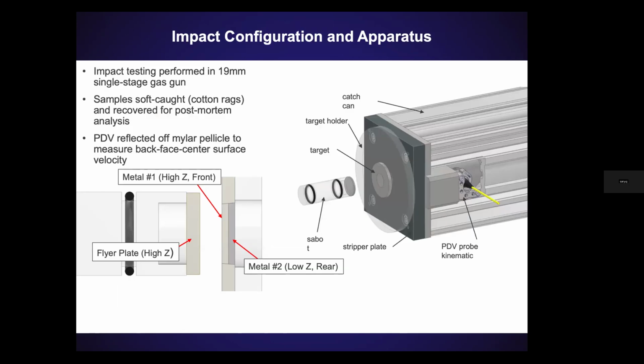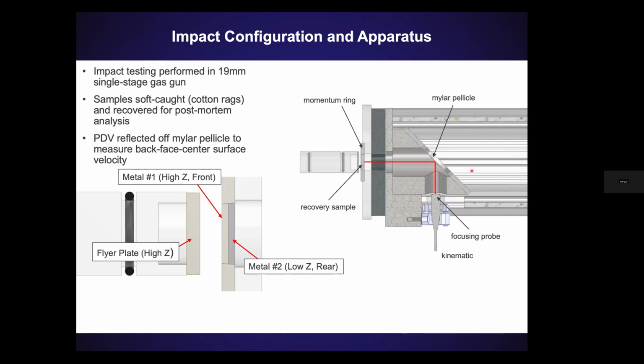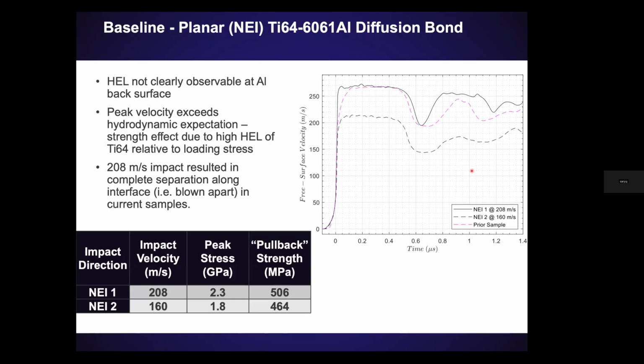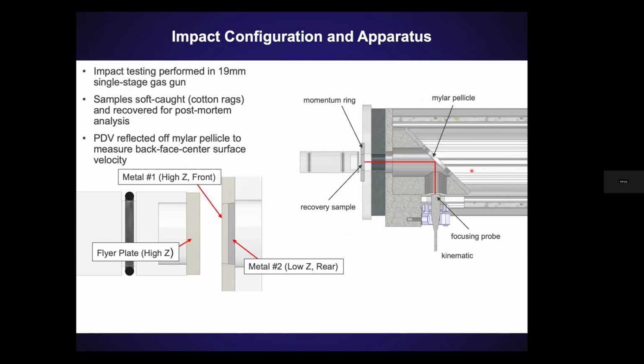And we did gas gun experiments again, where we captured this, soft recovered the materials and looked at them after. The first thing, I don't know how to calculate the spall strength in these materials, because one of the things that we took advantage of is there is an impedance mismatch between titanium and aluminum. As the shock goes from titanium into aluminum, you're going to get a secondary release wave at this interface. And essentially that release wave can interact with the release wave from the back and cause a separation of this interface just under shock. Don't even need to do spall.